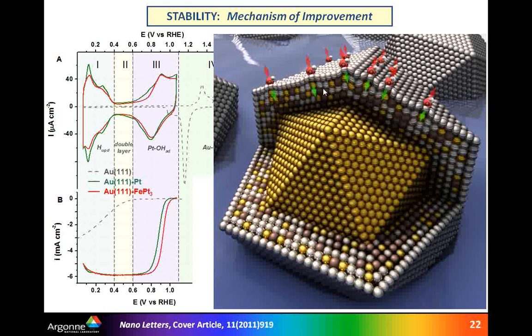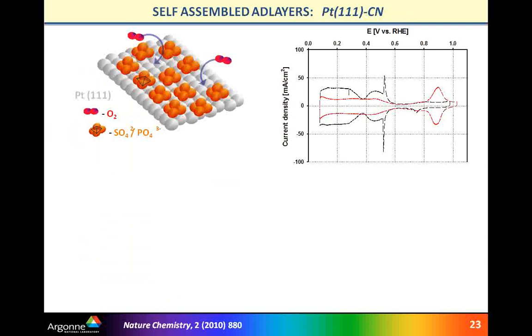In case that gold is not present, we wouldn't have so-called counterbalance effect, which is coming from the two opposing forces. One is from the subsurface gold, which has tendency to be on the surface, and the other one from surface oxides that are trying to pull platinum out, and in other words, to dissolve platinum. So that was our explanation of how we were able to stabilize.